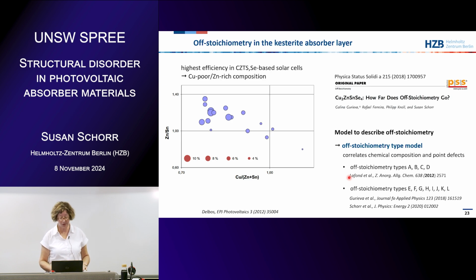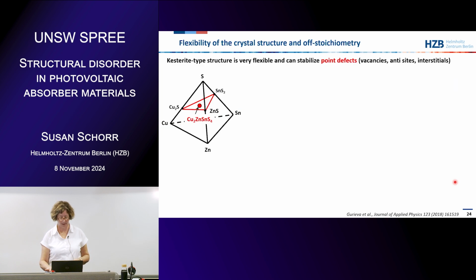He published it first, and he introduced the off-stoichiometry type model. He called them by capital letters, A, B, C, D. In this model, the chemical composition and the point defects are correlated to each other. Then we extended Alain's model to introduce more off-stoichiometry types, and now it goes up to L. I will show you on the next slide what this off-stoichiometry type means.